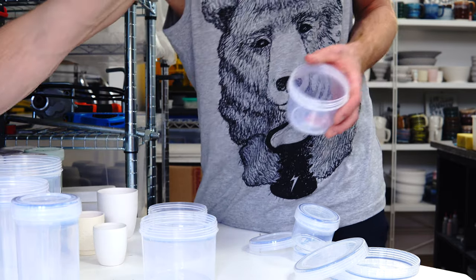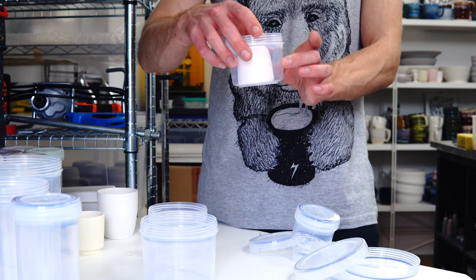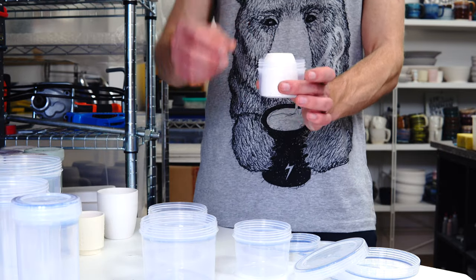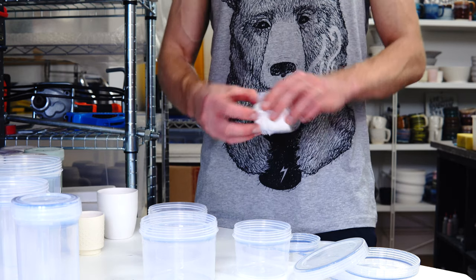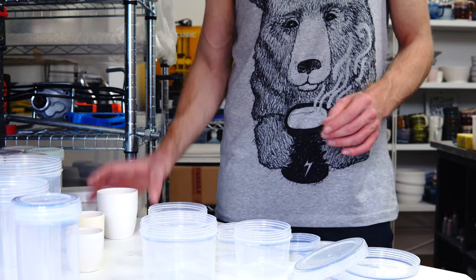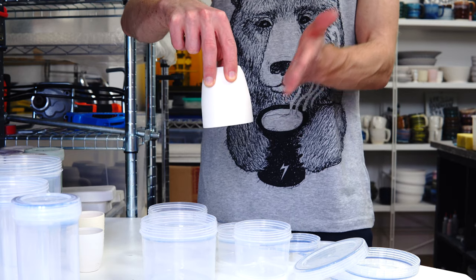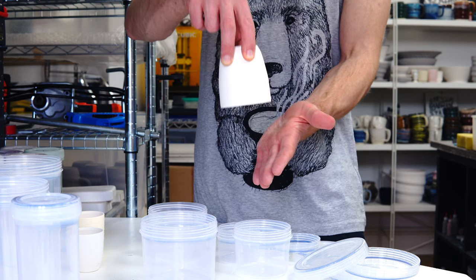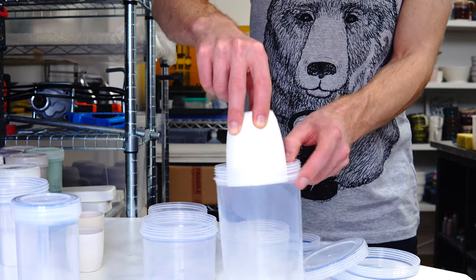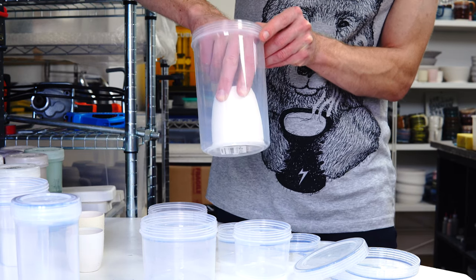Having something like this, you can displace enough that you only need it to be a fraction full. In fact, this one could probably even go in the smallest container — you'd be able to dip with basically no glaze and it would displace all the way to the top, giving you a full dip test with barely any glaze. The straight-sided shape is really useful because our pieces tend to taper towards the bottom, so if you're dipping that way you don't want the container to slope inward. With straight sides, wherever the piece reaches the glaze, it starts to displace and push the glaze up the side.